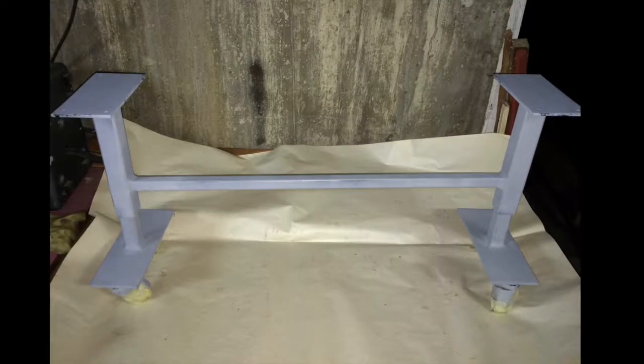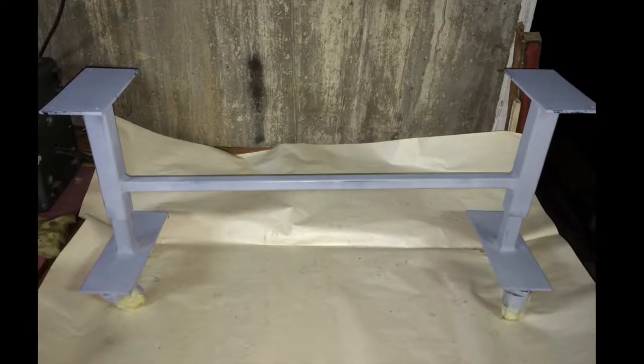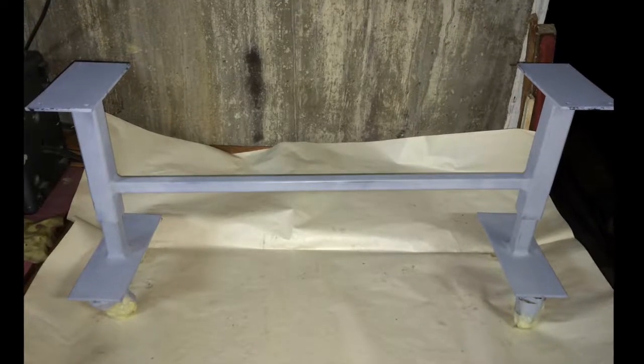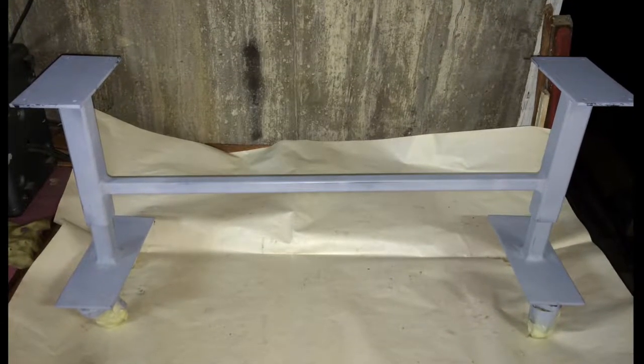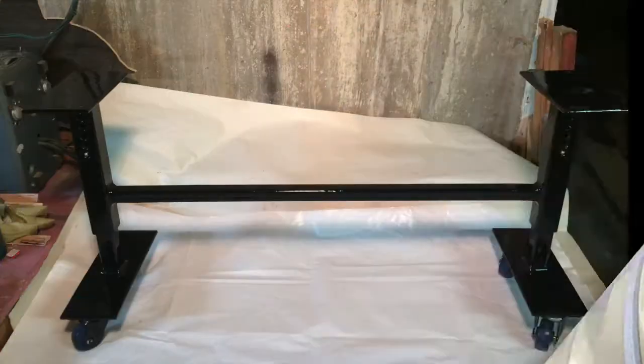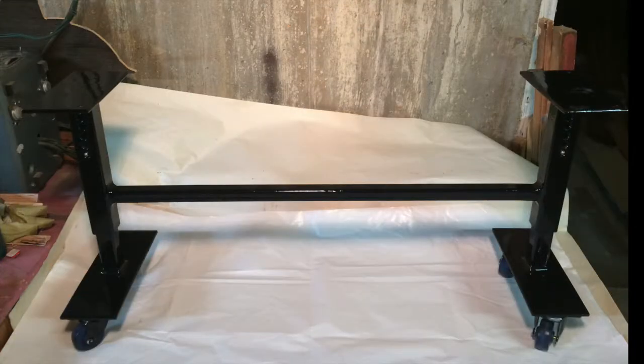Once all the steel work is done, a coat of gray primer coats all the steel parts. Next, all the steel is coated with glossy black. Unfortunately, the thickness of the coating became a problem for the telescoping legs, making them bind up. So I had to clean the 1-inch square tubes down to bare metal and spray the black coating on them. Then the coating was thin enough to let the legs telescope freely again, as you can see here.